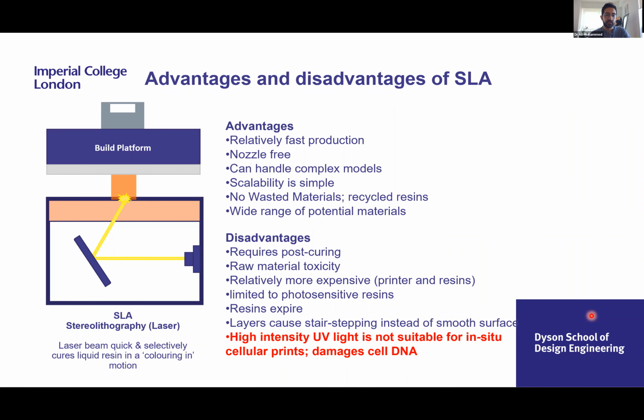Raw material can be toxic, and it's a relatively more expensive process due to the printer and the resins. It's limited to photosensitive resins, and the resins do expire. Even though you can recycle them, they have photoinitiators which can be consumed by oxygen and over time can be depleted. Also, you never get a smooth finish at the micro layer because you get a stair step rather than a smooth finish. And very importantly to highlight here, high intensity UV light is not suitable for in-situ cellular prints as it damages the DNA. The laser uses a 405 nm light, which is not suitable for bioprinting.